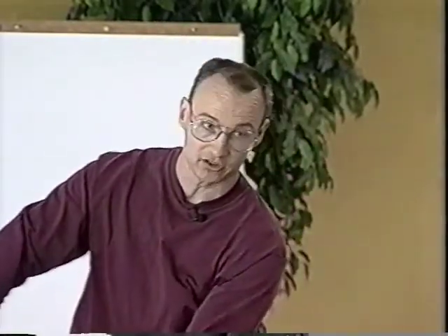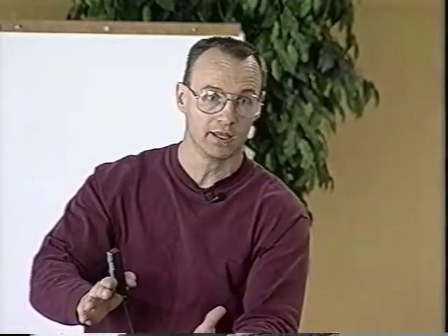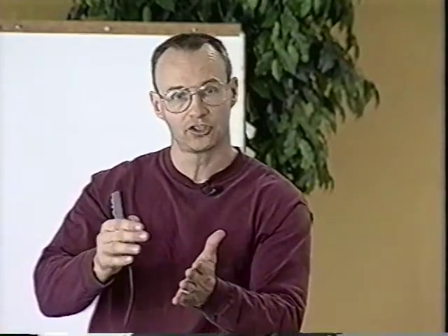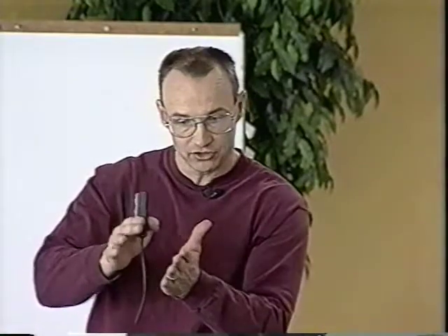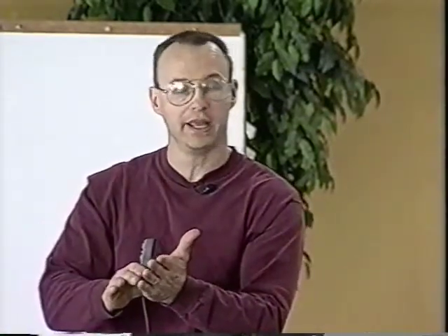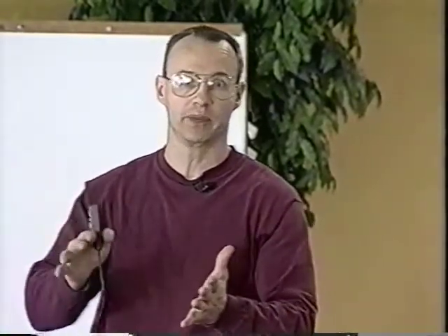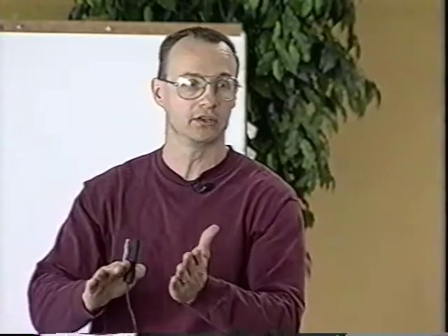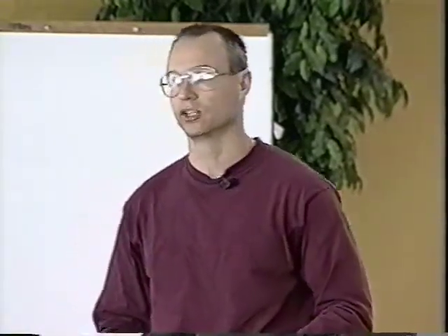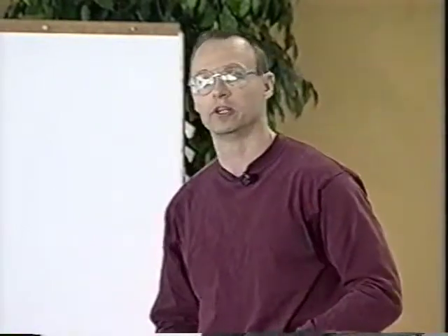As you're coming down through that process, as I said, you're liquid in the middle, and as steel solidifies, it tends to solidify out toward the edge and perhaps leave a little gap in the middle. And depending on what the chemistry of that grade is, that gap can really expand, and you wind up with cracking or splitting or some kind of segregation. There's a lot of chemistries where that happens more than others, and we just can't cast those chemistries. So we make plate.